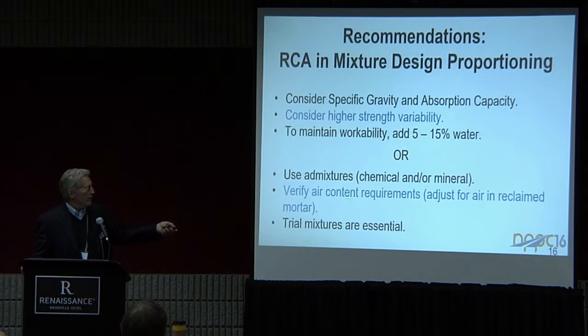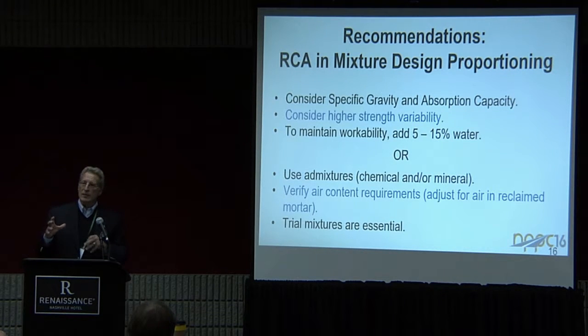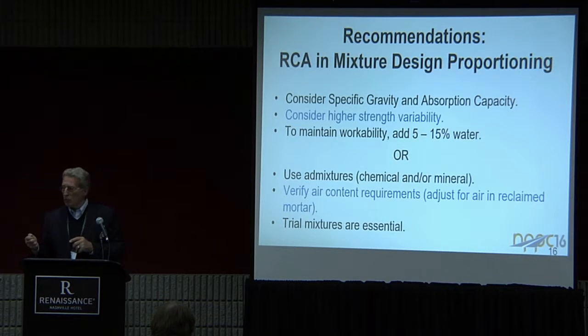Also want to verify your air content requirements. Sometimes if you've got a lot of air in the old mortar and you've got a lot of reclaimed mortar, your air pot's going to pick up that air and count it as total air in the system. So if you really want 5%, 6%, 7% in your fresh paste for durability, you may have to bump your requirements on the total air content up slightly, or else use a roll-a-meter to do it instead of using a pressure meter.